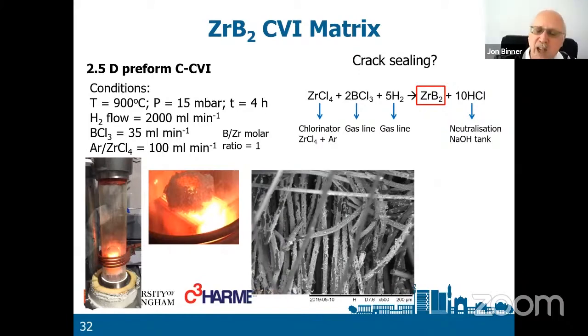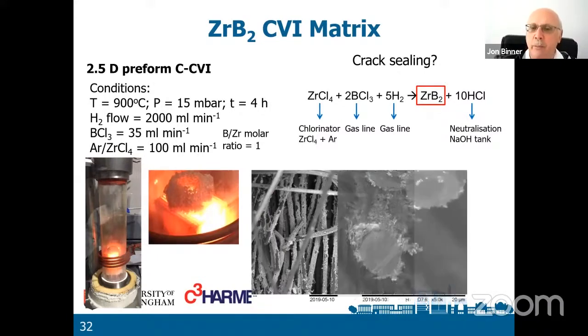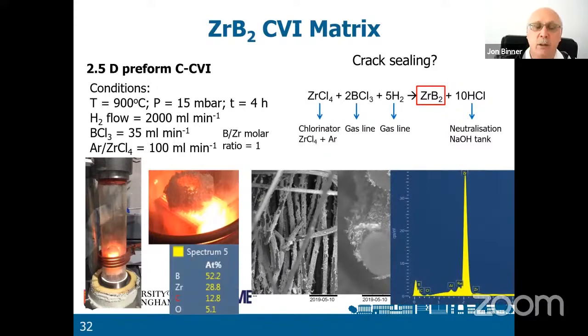So here is just after the first hour or so of deposition. You've got the fibers, you can see the deposits starting to occur on the surface of the fibers. If we zoom in a bit, you can see the fibers are quite nicely coated in the deposit. And when we analyze that, we find, yes, it is zirconium diboride. And the idea here is that in use, if you have any cracks, the zirconium diboride will oxidize to zirconia, and hopefully that will seal the cracks. So the idea here is to see if we can achieve some crack sealing, and therefore get even better materials.